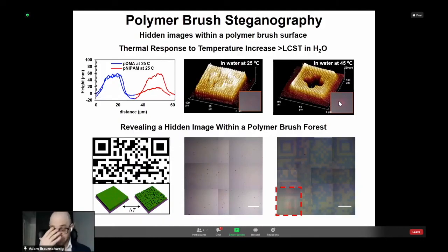But just to show that we can print over large areas and actually send an important message, he took this QR code and printed it on the surface. And then here you see the image of the QR code, and this GIF right here shows part of the image, this bottom left square that you can't actually see, appearing as you heat up the surface. So we call this a 5-dimensional hypersurface because to define any point on the surface, you need the X and Y coordinate, the Z coordinate, the chemical composition, and the response to temperature.